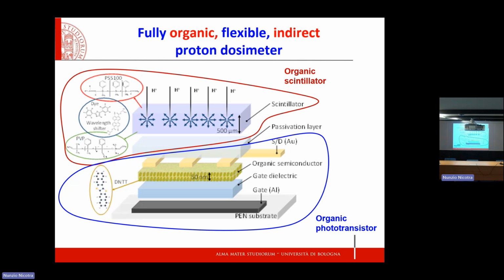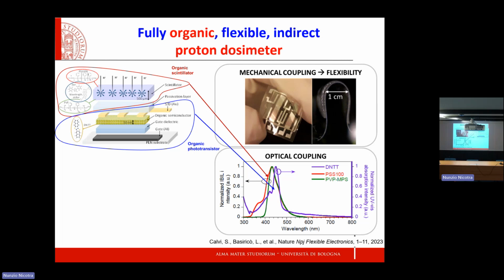Why do we change the molecule? Because we need a material that is absorbing exactly the wavelength emitted by our scintillators under proton irradiation. So you need to have a good optical match. That is what you see here. In purple, you see the absorption curve of the active layer of the organic device, the organic photodiode, and in blue and red, the emission wavelength of the scintillator. You see very nice optical coupling.